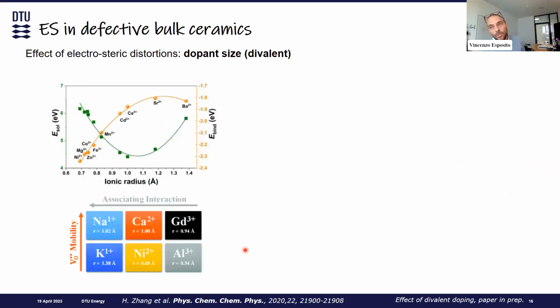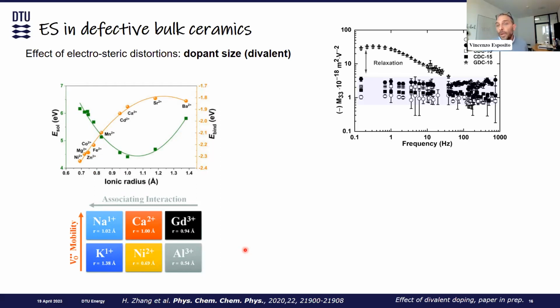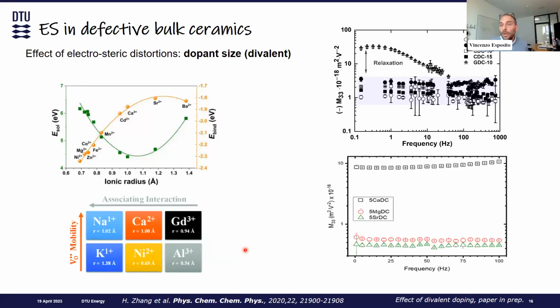So since there are many possible different dopants and many possible different combinations of dopants, we need to do some simulations with DFT models. So we have to take the atomistic picture of these materials and start putting artificially and numerically different cations in the cerium oxide lattice. And this is actually interesting because it gives us a hint of what can happen. For example, if instead of using a 3+ acceptor dopant, we use a 2+ acceptor dopant. And what we recently discovered is that, for example, calcium and magnesium and strontium suppress completely the low frequency response. So this is also a very important indication for us of how these materials are working.